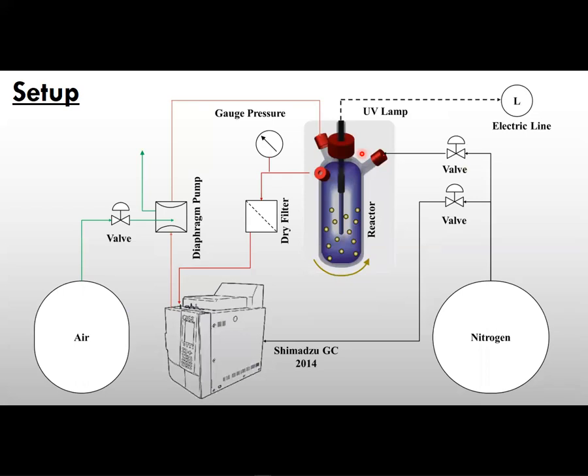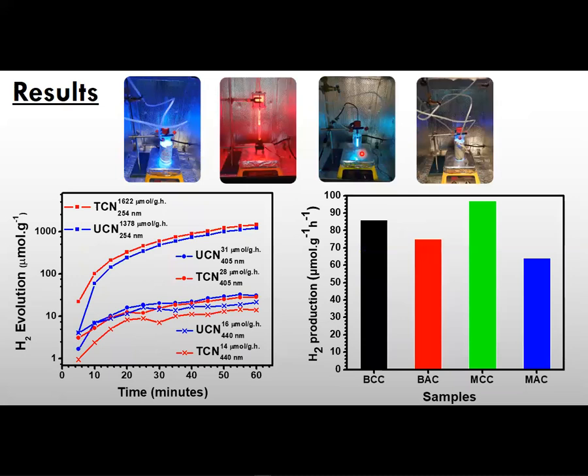In the center, you can see we have our reactor that contains the photocatalyst mixed with deionized water. Apart from the UV lamp that was used as a light source, we also carried out experiments using visible light. The visible light was acquired from LED strips that were spiraled around the reactor, as shown in the following images above.